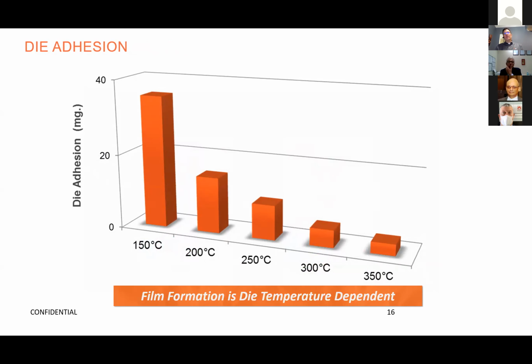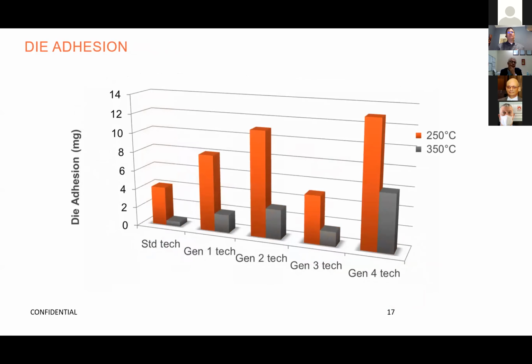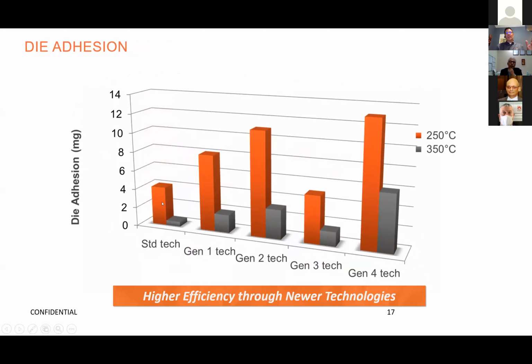Okay, so when we look at technologies for die adhesion, different generations — we don't really go by this anymore at Chem-Trend — but we have different generations of silicone technologies. As you can see, as we move through generations, not only did we get better die adhesion at higher temperatures and lower temperatures, but we were able to incorporate it in the ratio, so it's more effective at both temperatures. Now, when people look at this, they say, what's going on with that one you have marked Gen 3?